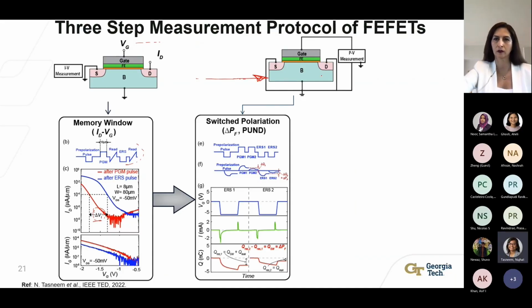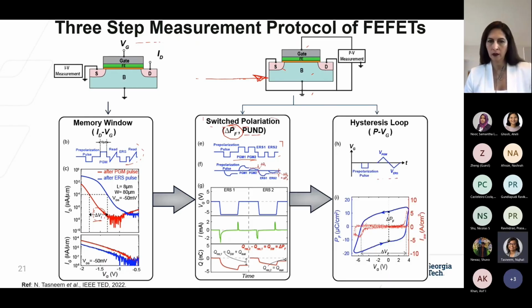Then we apply a positive up, negative down, or PUND, pulse sequence shown here to the gate terminal, while the shorted source, body and drain is grounded. This 2-pulse scheme in the PUND gives us the switched polarization in the ferroelectric layer, denoted by delta PF here, for the same erase program voltage combination. Right after that, we apply a triangular pulse to the gate terminal using the same connection for the same erase program voltage combination. And from that, we can determine the hysteretic PV loop for the gate capacitor of the FeFET shown here. From this PV loop, we can extract the theoretical memory window delta VP.